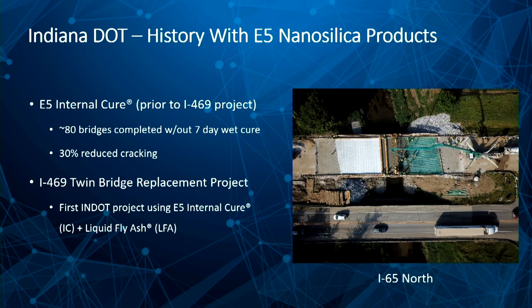Prior to the I-469 job, Indiana DOT had quite a bit of experience with these E5 products, the E5 internal cure specifically. They started using it and did their first bridge trial, I think, in 2016. They quickly recognized the benefits and the potential of it, and by way of memo, not specification, after seeing about 80 bridges in place with 30 to 60% reduced cracking, they wrote a memo that allows contractors an alternative to 7-day wet cure. You use the E5 internal cure, it consumes the water of convenience, so there is no bleed water, and ultimately you can remove the 7-day wet cure process. The materials, the cost, the carbon footprint, all of that.